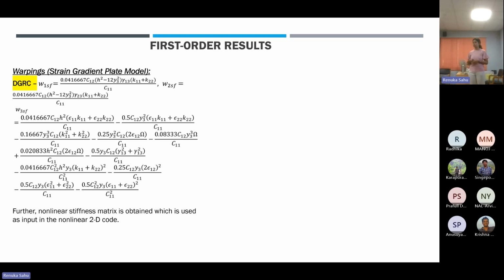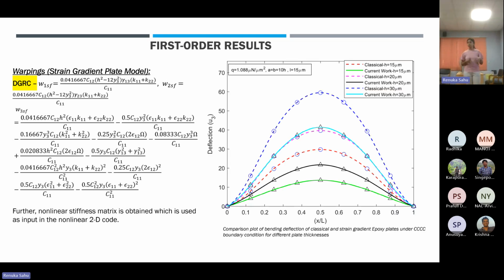That is used as an input in a nonlinear 2D code to do the loading studies. Here we have a comparison plot of bending deflection, classical and the current strain gradient model, under all edges clamped case. As you can see, because of the nonlinear stiffness terms obtained in the first order, the deflections are very, very high compared to what we got in the zeroth order strain gradient model, because of the nonlinearity which comes into play here.